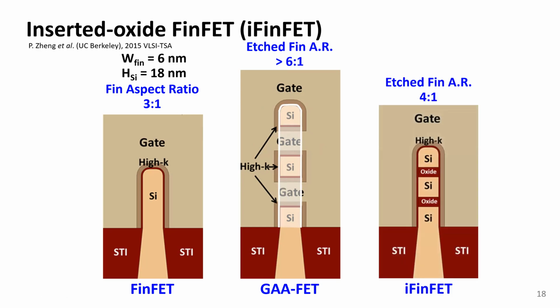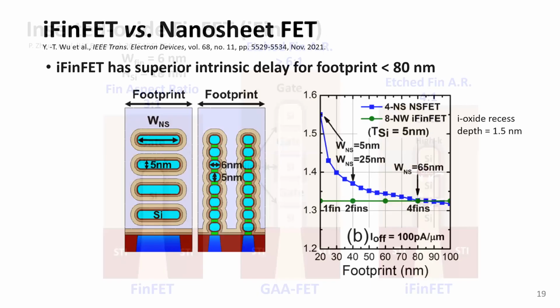So for that reason, we proposed, rather than putting the entire metal gate stack in between each silicon channel, why don't we just introduce only a simple oxide layer in between each channel region? So this way we can have a much shorter stack than the gate all-around FET requires. So it's easier to manufacture. And this oxide layer allows fringing electric fields from the gate electrode to penetrate in the channel region to help control the electric potential of the channel for improved gate control.